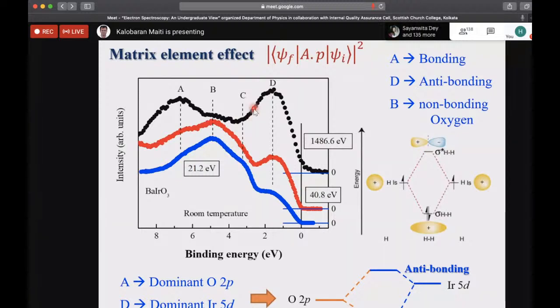For example, if you use an X-ray source, the iridium 5d states become much stronger compared to the oxygen 2p state. But if you are at 21.2 electron volts, then the oxygen 2p state becomes much stronger compared to iridium 5d. Now you can see that in this spectrum, this peak is very strong compared to this one in XPS, or X-ray photoelectron spectrum. So that way you can say that this one is dominated by the oxygen 2p state. Similarly, this one is dominated by iridium 5d states.